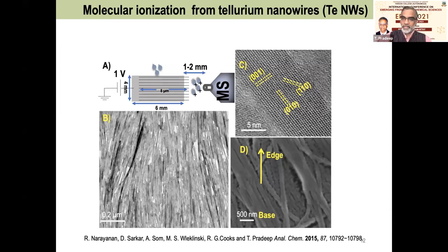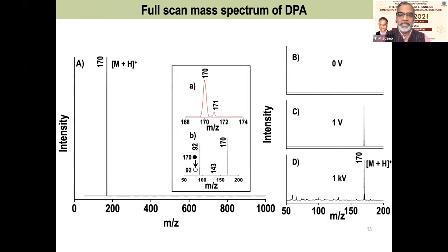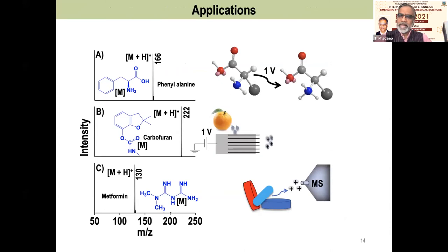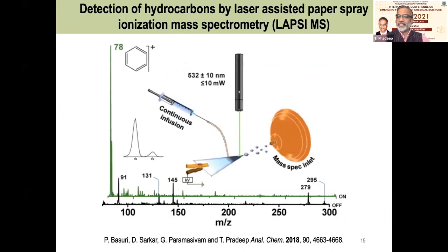Now we have taken this further. We take a nanomaterial called tellurium nanowire. So these are nanowires. You can put this on a surface. And you put a solution there, you get again similar ionization. Now, one very interesting thing is that these wires, let's say they are all oriented in a particular direction, you rotate this direction. So instead of sitting like these, they are sitting like these. Then you can stop the ionization. So such things were studied at some point in time. So these are some details of that. Some applications of such methodologies.